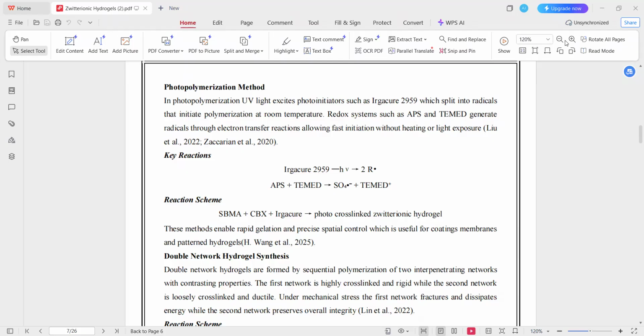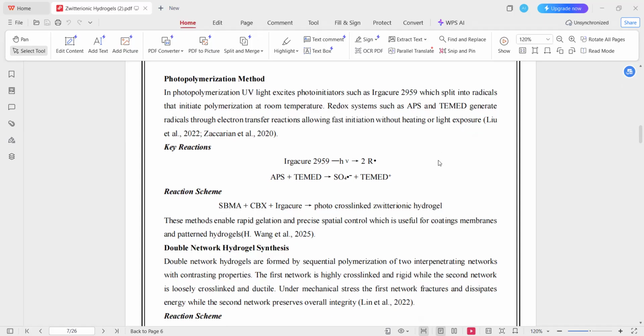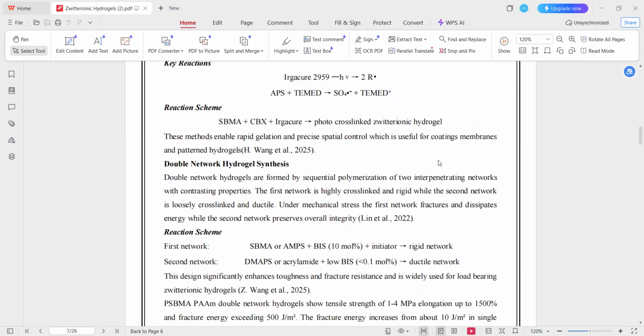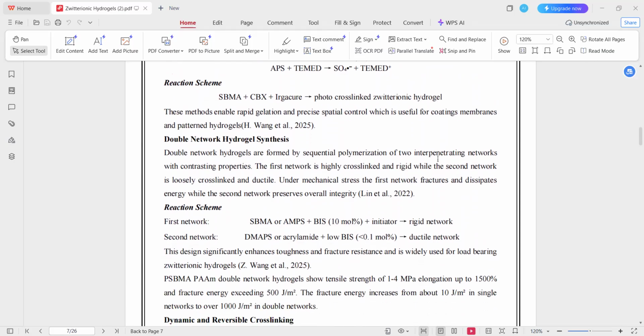The next method of synthesis is double network hydrogel synthesis. To overcome the mechanical weakness of conventional zwitterionic hydrogels, double network hydrogels have been developed. In this approach, two interpenetrating polymer networks are formed sequentially within the same material. The first network is highly cross-linked and rigid, while the second network is loosely cross-linked and flexible. The first network is designed to act as a sacrificial network. Under mechanical stress, this rigid network fractures and dissipates energy. The second network, which is more elastic and ductile, maintains the overall structural integrity of the hydrogels.